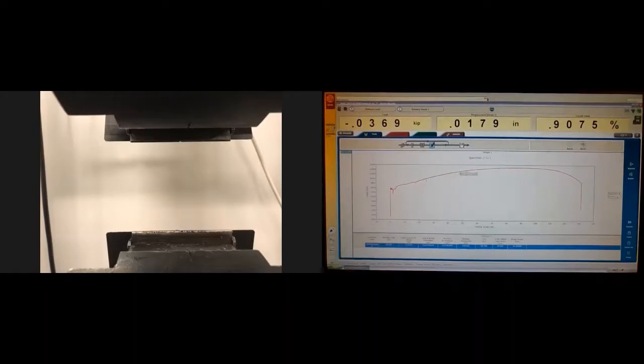And this is where the straining of the material is associated with hardening, so strain hardening. And from this point up until this maximum point, this difference is called strain hardening capacity of the material. And once we've reached this maximum point, we've exhausted all homogeneous deformation, all capacity of the material to be deformed plastically without failure. So after this point, neck started to occur, and from here to the end, there is inhomogeneous deformation, which is associated with neck and localized stress and deformation.